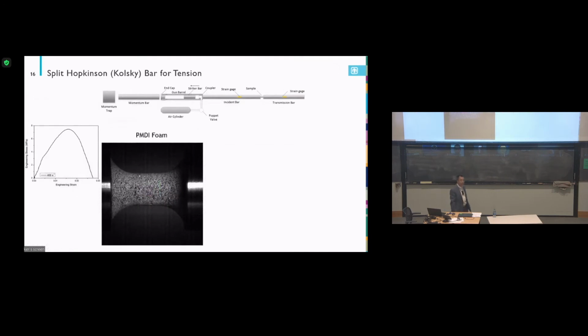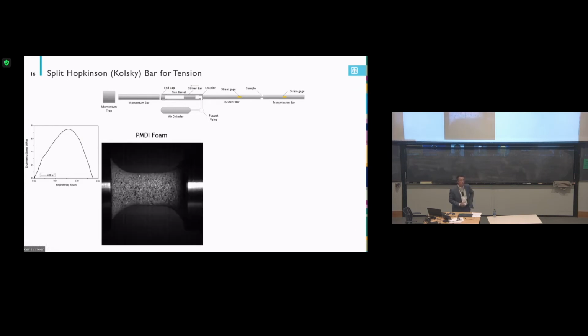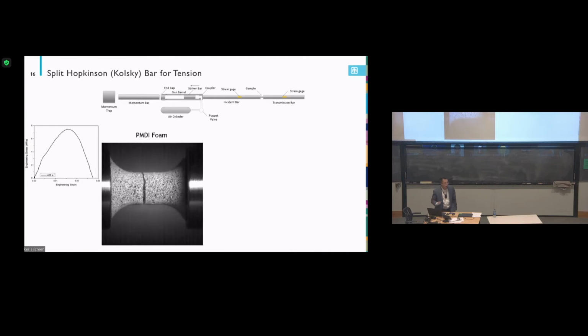And foam, you still remember the foam compression test, you got yield, plateau, and densification. But when the foam is subject to tension, it's just like a brittle material, just directly cracked and fractured. So you can see the stretching curve is nearly linear like this. So it's quite different from the compression test.